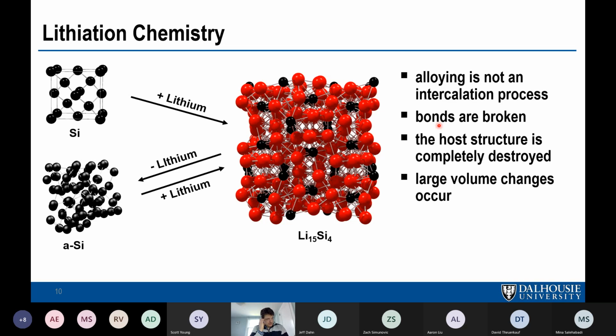So why don't we just replace graphite with silicon? Well, it's hard. And the first thing you notice is the chemistry with lithium is very different. If you lithiate graphite, there's lots of room between the layers that are widely separated. They're only held together by weak van der Waals forces. And the lithium can go between the graphite layers without changing the structure or expanding the volume very much.